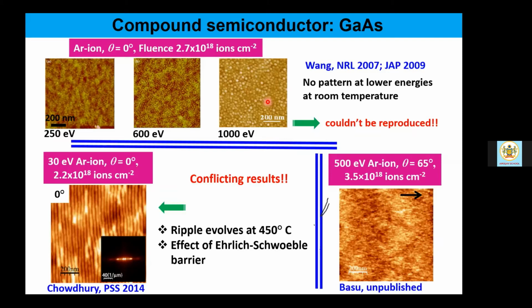And this has been attributed to the Ehrlich-Schwoebel barrier. I'm sorry for this mistake in spelling. This last E should actually be interchanged with the L. Anyway. But for a little higher energy, we get to see, for instance, at 500 electron volt of argon ions, when you consider an incident angle of 65 degrees with again comparable ion fluence, a flat surface.